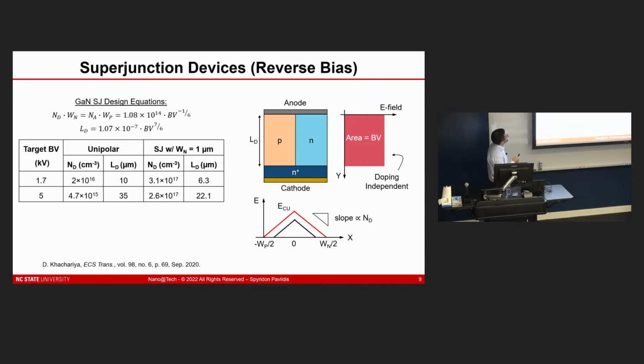So let's take the 5 kV case. If you're doing this with a unipolar device, again, you'd have to be in the mid 10 to the 15 doping range, so very low doping with thick 35 micrometer thick drift regions. Now, if you've got a superjunction device, and you can scale this to have very small pillar widths, now your doping relaxes, and you can do this at 10 to the 17, and a slight improvement or relaxation of your thickness requirements as well. But really the main benefit, as you can see here, is almost a 2 orders of magnitude increase in the doping that you need.